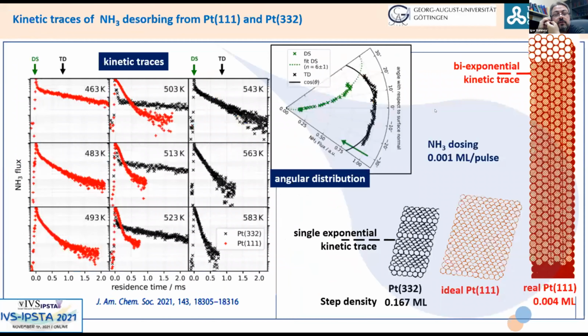And this is how these time-resolved desorption fluxes look in real life. So what we are doing in this experiment, we are using two surfaces. One of them is platinum 332, a highly stepped surface with 16.7 percent monolayer of steps. The other is platinum 111, which in the ideal case, of course, is absolutely flat. In this realistic case, the density of steps is 0.004 monolayers.